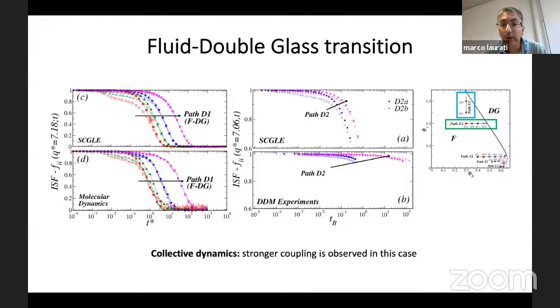And in the collective dynamics, we can still see the coupling, which you see even much stronger in the case of the fluid to double glass transition, because when we are really close to the transition, the dynamics are essentially identical. And this was also, in this case, nicely shown by the DDM experiments. Again, the lines are slightly different, but the qualitative behavior is clearly reproduced by all techniques.